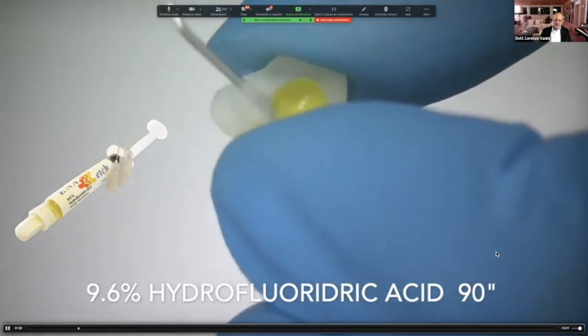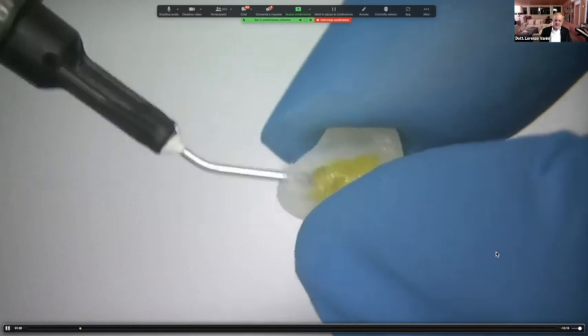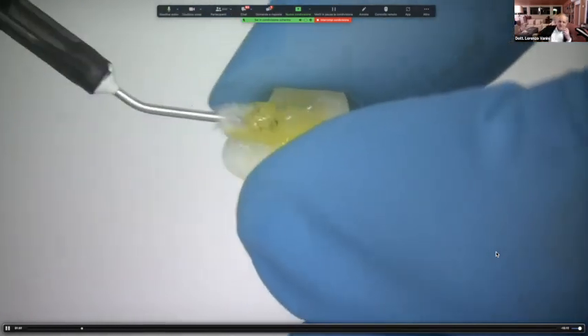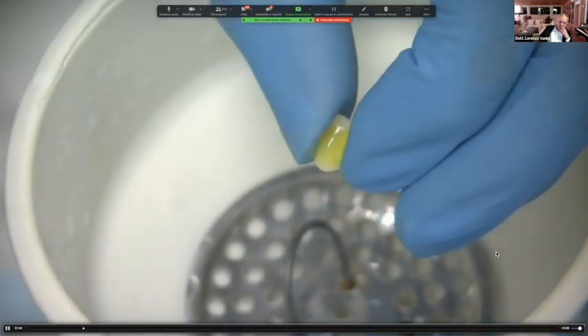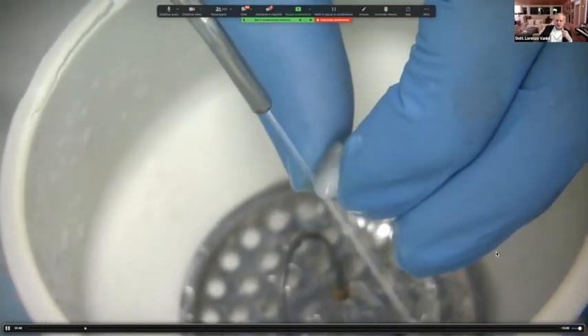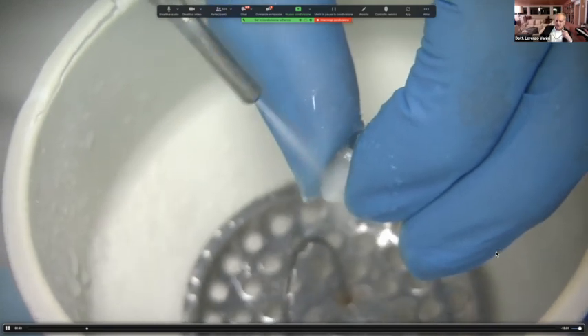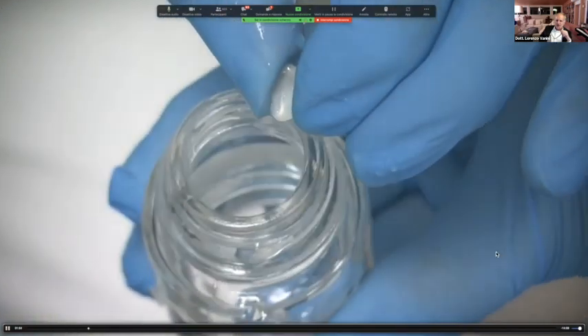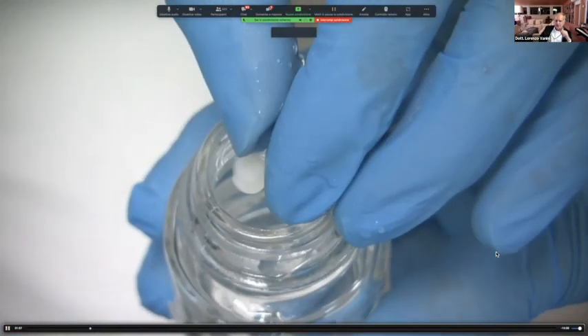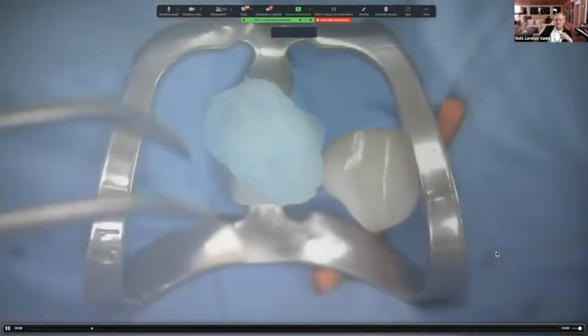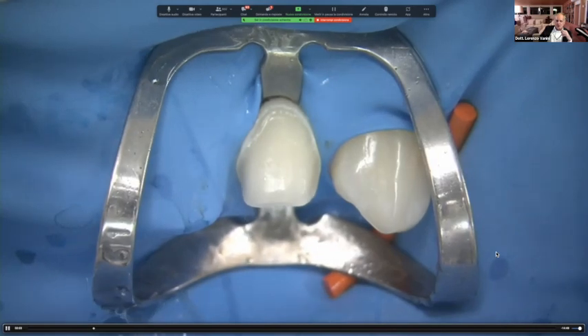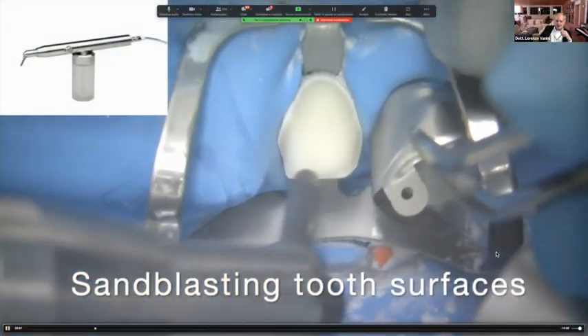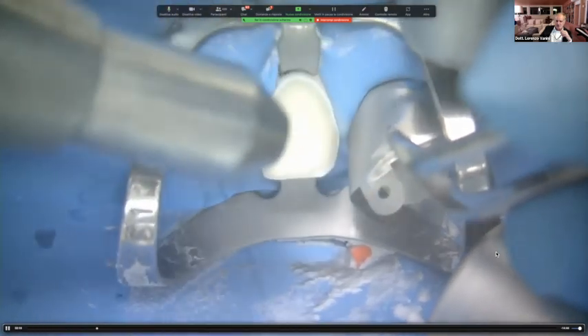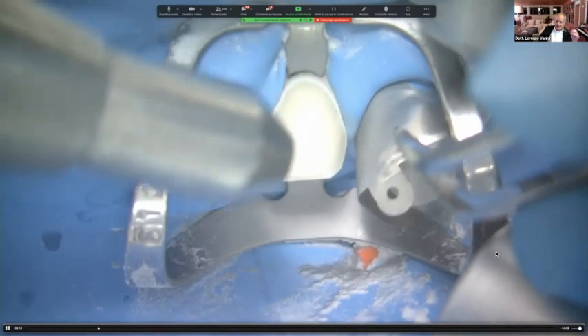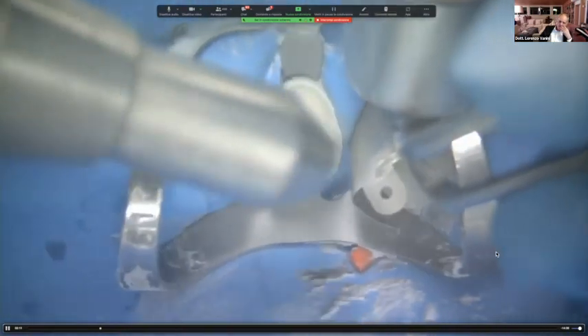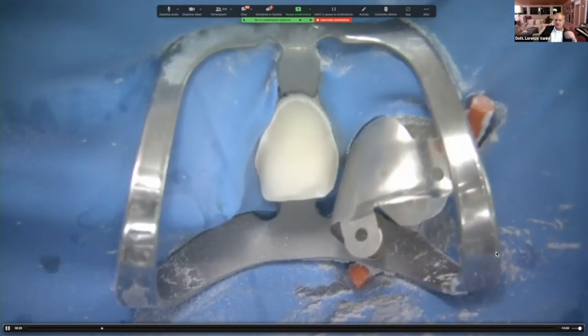I am etching the laminate after the sandblasting treatment. Hydrofluoric acid 9.6%, 90 seconds. You have to rinse very well with water and put in the ultrasonic system for 5 minutes. Sandblasting of the tooth surfaces in order to completely eliminate all the bonding. Rinse very well with water.